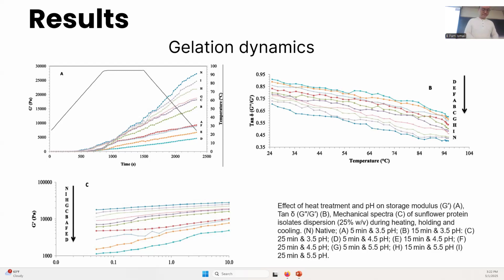So it was observed that the G prime value increased with temperature for all the protein isolate gels, indicating the formation of stronger gels upon heating. The denaturation and the exposure of hydrophobic groups enhance the protein-protein interaction, which results in stronger gel, and was evidenced by the increase in G prime value.